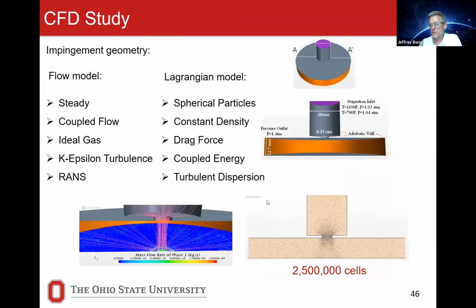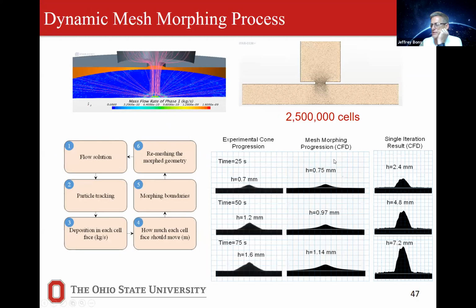We're looking at different ways we can account for the buildup on the surface. So this is a simulation where we have a particle flowing through this jet onto the surface, and it creates these mounds that we saw before. And in this case, this is the experimental progression. And this is the computation that we've derived to try to model that.